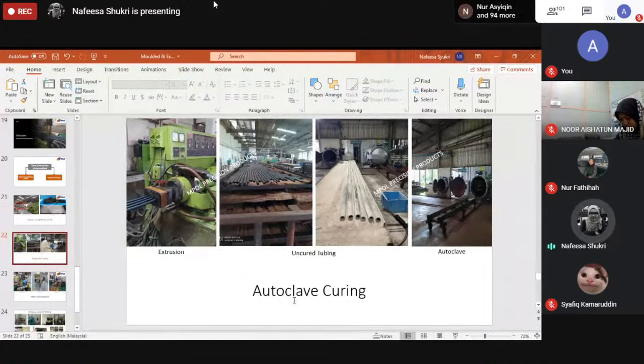So basically the difference between autoclave curing and LCM curing is that LCM will produce the cured rubber product directly. However, for autoclave curing, it will extrude out the uncured tubing. So we need to put this uncured tubing into the autoclave. You can see here there are two types of tubing I'll show you.